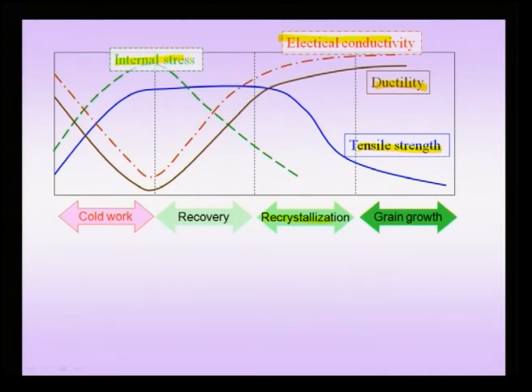Now what happens during cold work? So I have this process till this line here, which I can call the cold work regime. What happens to these three properties in the cold work regime? You can see clearly that the electrical conductivity, which is shown in red, is seriously hampered by the increase in point defect density, and of course also because of dislocation density. So what is happening is that the electrons which were moving unimpeded, who had a larger mean free path, are now scattered because of the presence of these defects which distort the lattice, and there is a decrease in electrical conductivity. And the ductility also decreases during cold working, and of course the benefit we get is in terms of the tensile strength. That means my strength increases, but my ductility comes down, and this is what happens during cold work. And of course because now my overall strength is coming from one of the important factors being dislocation density, the internal stress also increases.